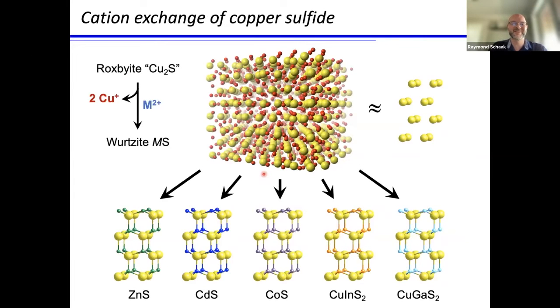Probably our favorite material is both simple and complex at the same time. It's roxbyite copper sulfide. I have the formula in quotes. There's a lot embedded in these quotes. It's really Cu1.8S. I'll simplify it to Cu2S for now, but know that there's a lot of chemistry involved in that simplification. But suffice it to say that you can take this copper sulfide material, these are colloidal nanoparticles, just in solution, kick out 2 of the copper +1 cations and insert 2+ cations, or even in some cases 3+ cations from solution to do this exchange reaction.